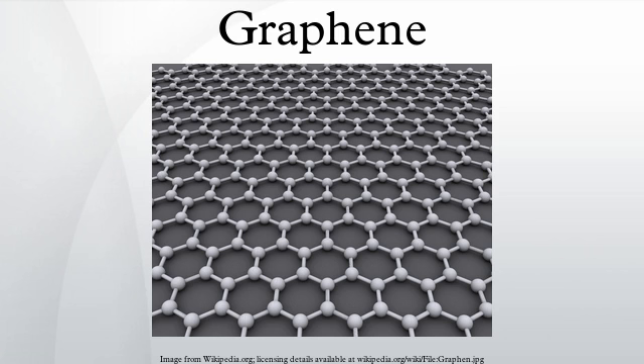When the wafers are heated to approximately 1000 degrees Celsius, silicon is preferentially driven off along the edges, forming nanoribbons whose structure is determined by the pattern of the three-dimensional surface. The nanoribbons had perfectly smooth edges, annealed by the fabrication process. Electron mobility measurements surpassing 1 million correspond to a sheet resistance of 1 ohm per square, 2 orders of magnitude lower than in two-dimensional graphene. Graphene electrons can cover micrometer distances without scattering, even at room temperature.